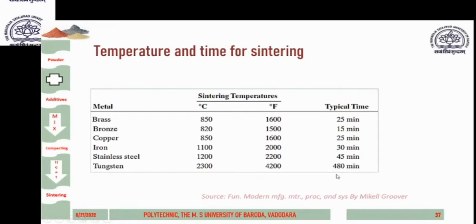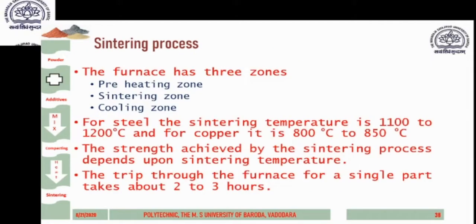In this way we get the time and temperature cycle, and these cycles must be operated properly to get a good quality job from the powder metallurgy green compact. The furnace has three zones. You can take notes of this. The furnace has three zones: preheating, sintering, and cooling zone. For steel, the sintering temperature is around 1100 to 1200 degrees centigrade, and for copper it is around 800 to 850 degrees centigrade.